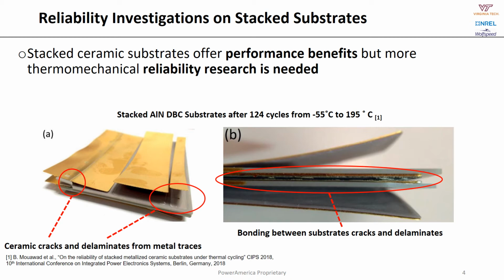As you can see from the existing research, this stacked aluminum DBC, direct bonded copper substrate, has cracking in the ceramic and delamination of the metal traces from the ceramic substrate, as well as some failures in the bond between the two ceramic substrates in the stack earlier than 150 cycles, thermal cycling between minus 55 and 195 degrees centigrade.